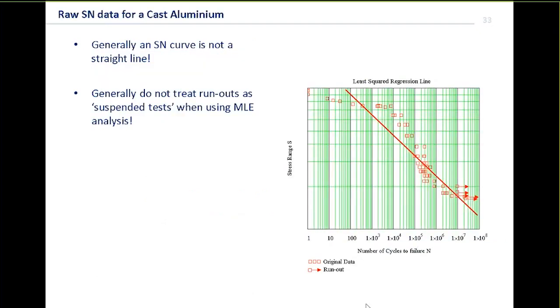Now, when we try and fit a curve, just two things to remember. First of all, an SN curve is not a single straight line. Typically, as we'll see in a minute, the SN data has three distinct regions. So make sure when you're fitting a straight line, you're fitting it through the correct region, otherwise you're going to get the wrong results. And the other thing is, if you come from a reliability background, a fatigue test, an SN test, is not the same as a reliability test. You can't use MLE and use the suspended tests for that.